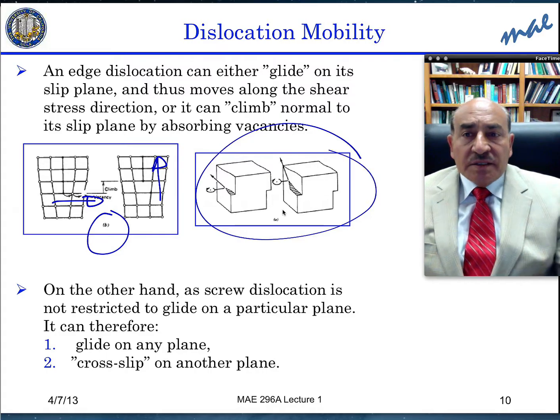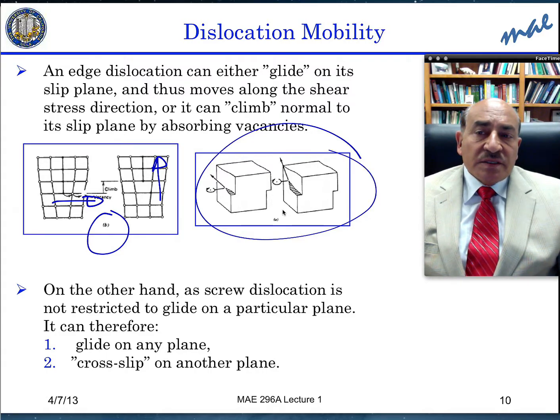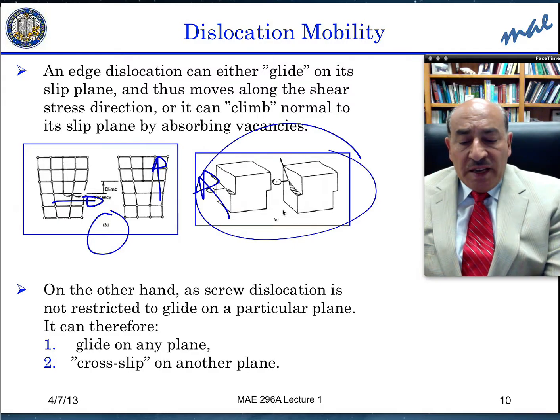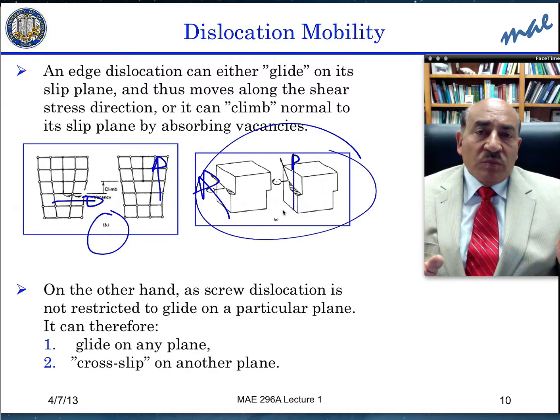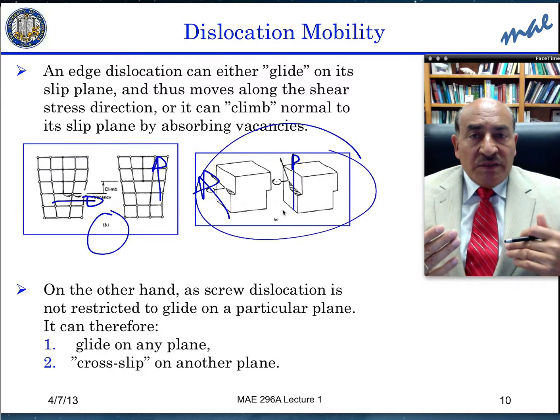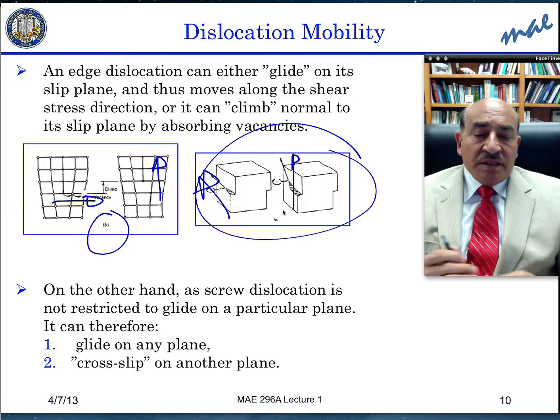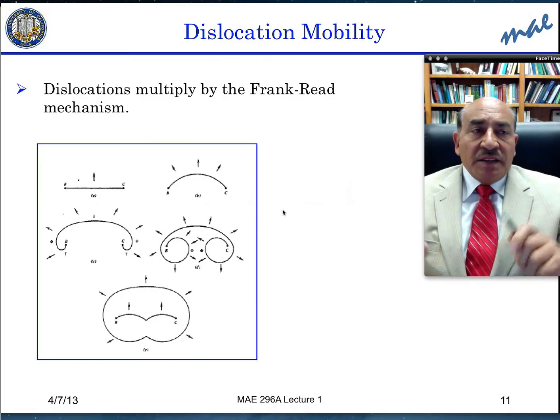On the right hand side here, you see a screw dislocation, and the screw dislocation can move either on a glide plane, or it can cross slip and move on another glide plane. The screw dislocation is not necessarily confined to move on its glide plane, and it can move on any conjugate or similar plane in the material. If it meets an obstacle like a precipitate, it avoids this obstacle by crossing over to another region in the crystal and continuing to move. So screw dislocations are very slippery, and they can move around easily.